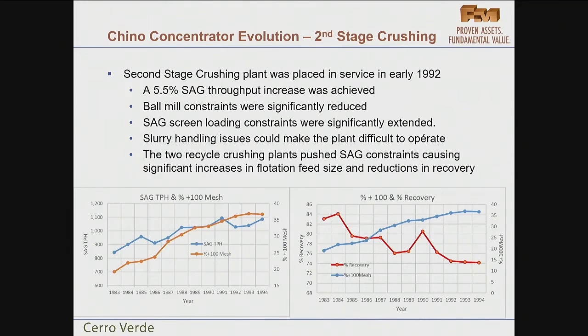So the second stage crushing plant went into service in 1992. We got a throughput increase compared to the conditions of the time, and the ball mill constraints were significantly reduced. So were the SAG mill loading constraints, because this material was not coming around anymore. But slurry handling issues made the plant difficult to operate at times.